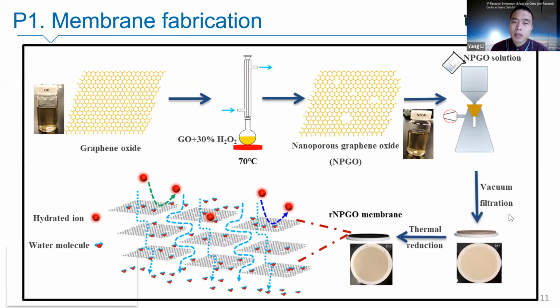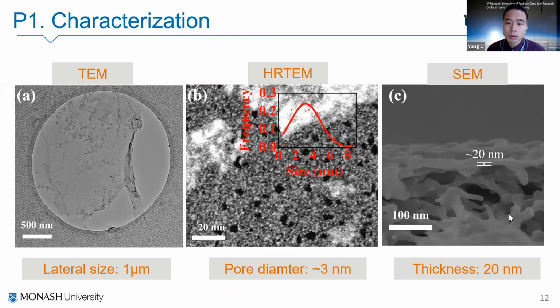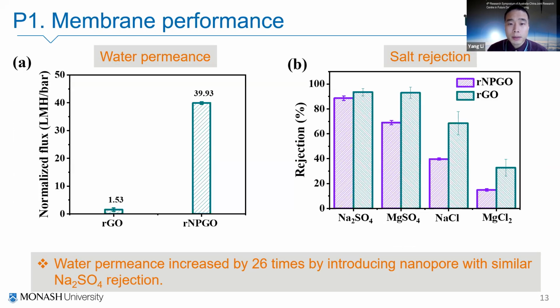We first get the nanoporous graphene materials, and then through filtration, we get a laminar membrane. After that, we reduce the membrane to get the nanoporous membrane, which is somewhat reduced to be stabilized. From the TEM or SEM results, we get to know that after introduction of nanopores, the lateral size is around 1 micrometer, the pore diameter is around 3 nanometers, and the membrane thickness is around 20 nanometers. We compare the membrane performance with those that have not been modified. We found the water permeance is significantly increased by 26 times, and the salt rejection for sodium sulfate is pretty similar.